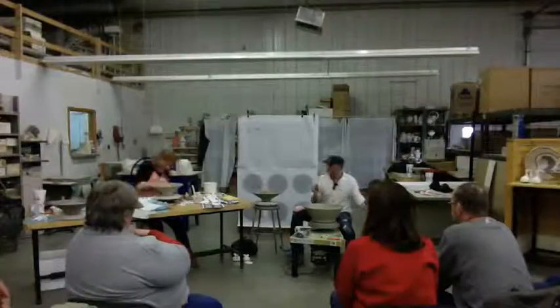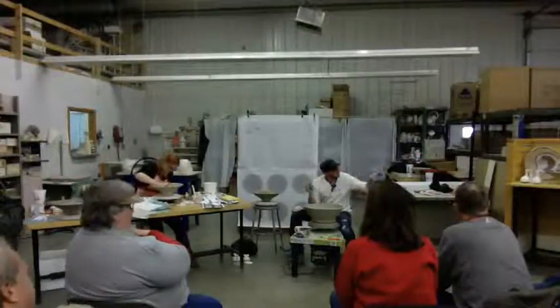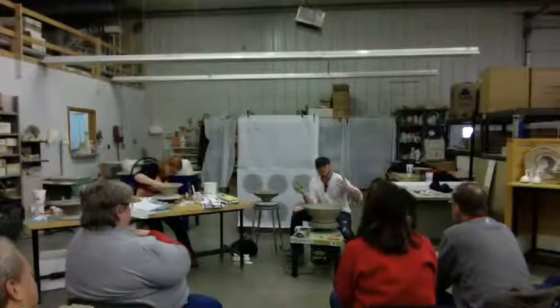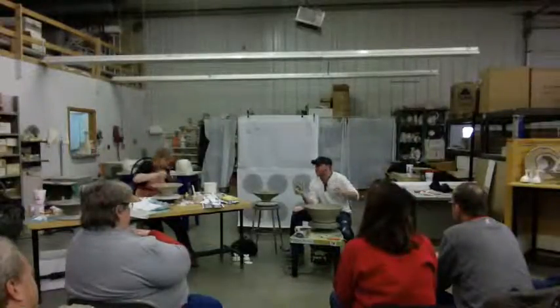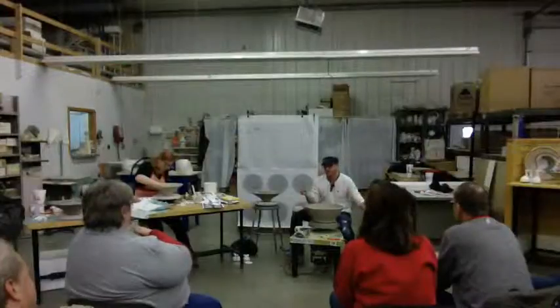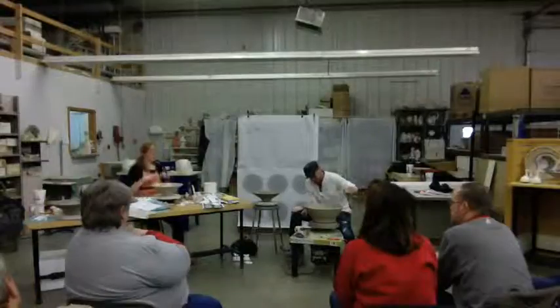I use little circle stickers for the insides of my squares, but when I put the glaze over it and walk off, I forget where they're at. And you'd be surprised, when you fire stickers, that sticky residue does not burn off. I've forgotten a dot here or there, and it's not a good thing. You'd think it would just burn out and be fine.